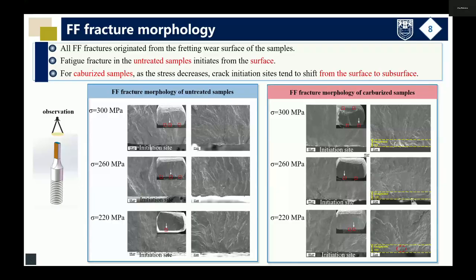Using SEM, we examined the fretting fatigue fracture morphology. The result shows that all fretting fatigue fractures originated from the fretting surface of the sample. Fatigue fracture in the untreated sample initiates from the surface. In contrast, for carburized samples, as the stress decreases, crack initiation sites tend to shift from the surface to the subsurface.